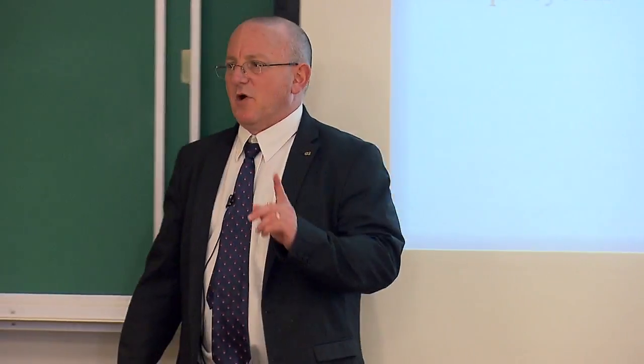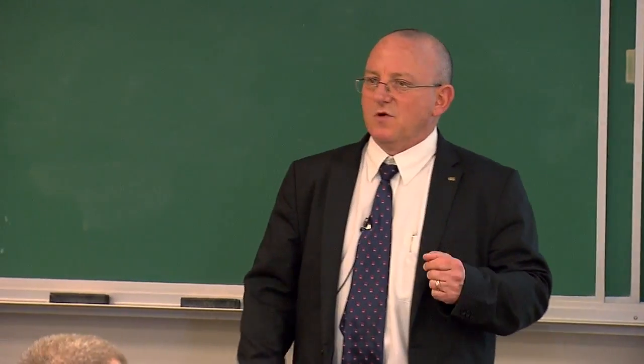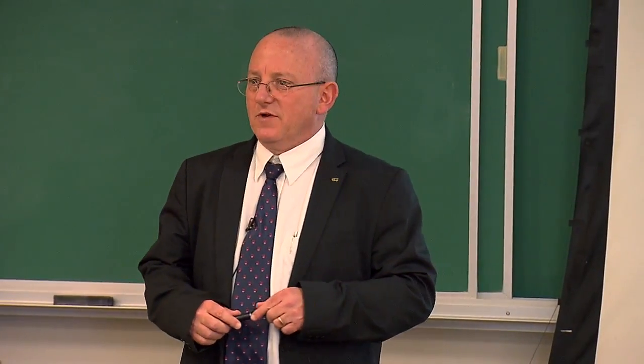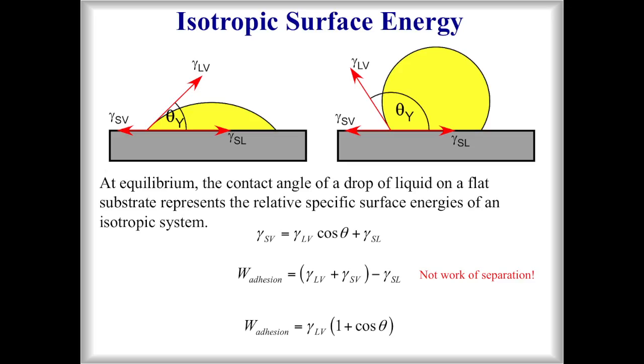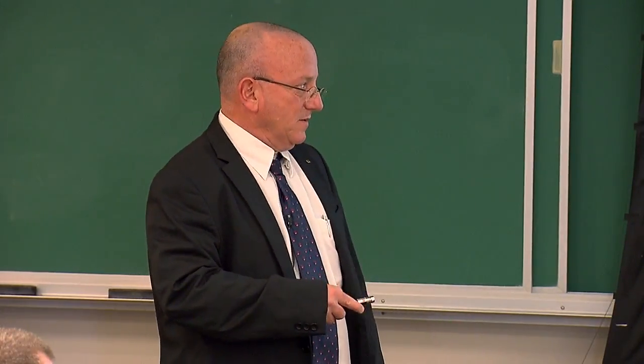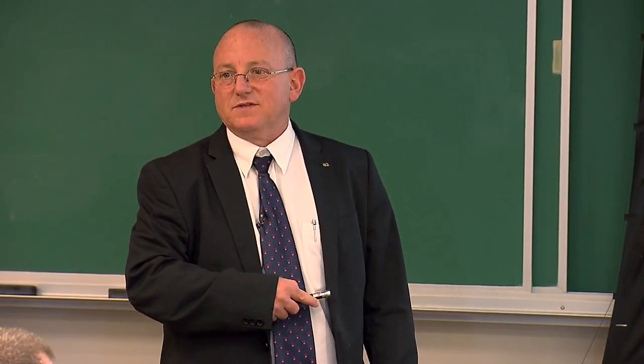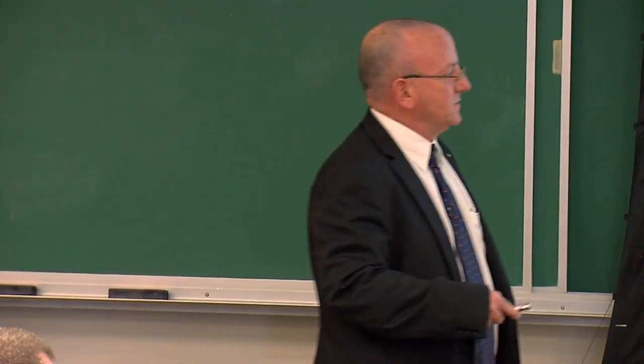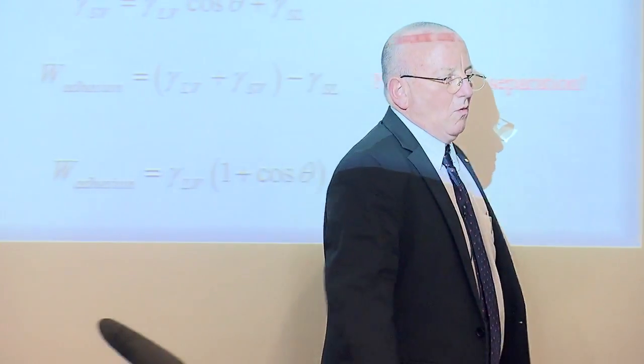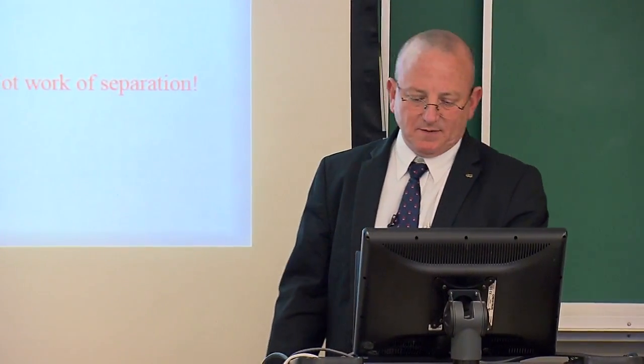Here, we're just looking at an experimental contact angle, an experimental energy of the surface of the liquid, and we can get out the thermodynamic work of adhesion. And that's a value that we can compare between system to system, as long as we remember that it is not the thermodynamic work of adhesion after that little drop solidifies. So if you're trying to get at, I don't know, some kind of composite, for example, between a metal and a ceramic, and you're looking at a contact angle of the metal liquid droplet on the solid, and we were to solidify it, then I promise you that the thermodynamic work of adhesion is going to be different after it solidifies. Unfortunately, people sometimes forget that. So why is Young's equation not correct, or why does it bother me?